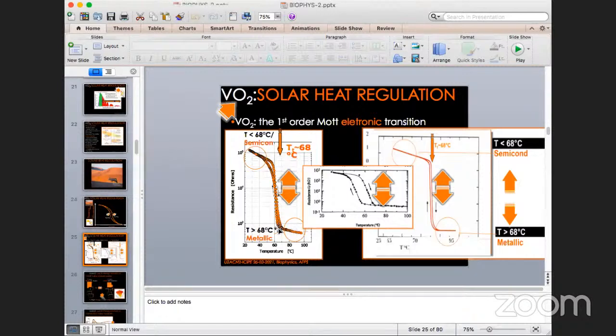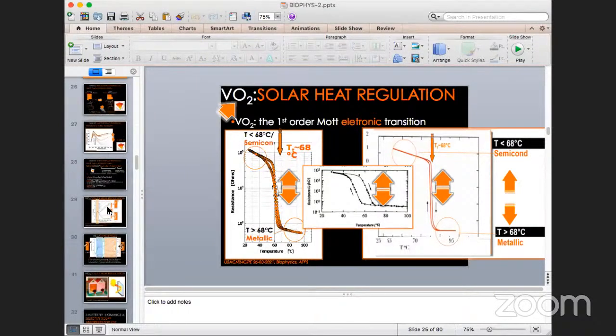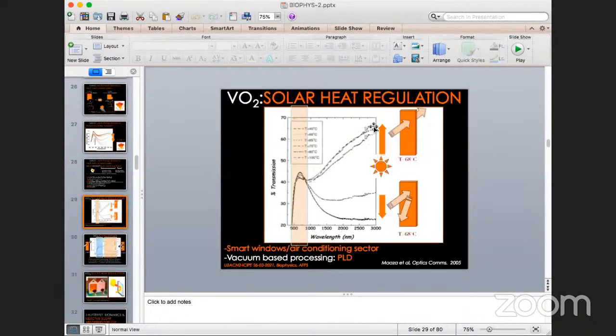But when you dope with the tungsten, unfortunately, the modulation, this modulation here. Well, let me just go to the optical one. The modulation, the maximum transmission to the minimum transmission. When you dope with the tungsten, this modulation, the value of the gap, decreases. So we are working on other strategies, in parallel strategies, to reduce the temperature while keeping this modulation large. But there are quite a number of groups worldwide now working on it.